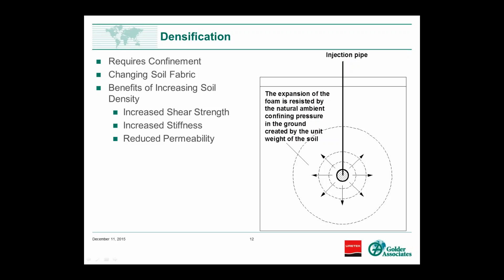The little schematic here shows you the general idea. I should mention that the pressure is not applied by the injection gun. The pressure that's causing this densification is from the chemical reaction itself. So it's happening at the injection point, and it's relatively independent of the pressure at which they inject it at the surface. This is what's happening down below. And it's probably not quite that uniform either.